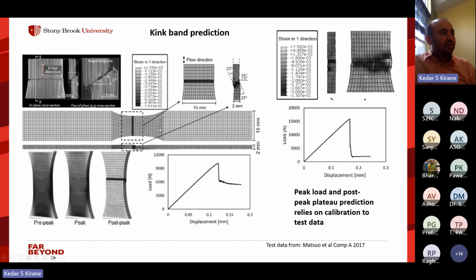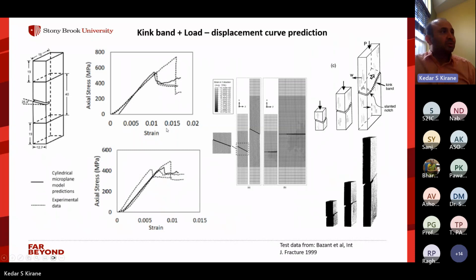But I have to say that under loading which is aligned with the fibers, the more preferred form is out of plane kinking. At least that's what the observations suggest. Now, the load versus displacement curve for another test set of experiments we modeled. You can see here that these were notched compression tests, and the solid line is from the model and the dotted is from the experiments, and you can see that the agreement is pretty good.